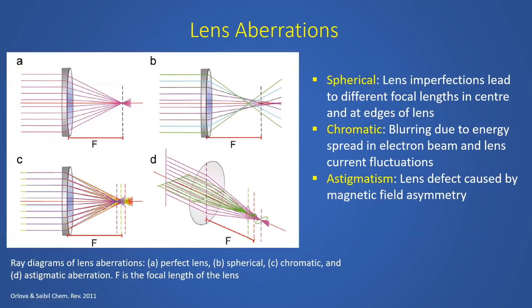These are the lens aberrations that you have typically with any microscope: spherical aberration, chromatic aberration, and astigmatism. Spherical aberration basically results from lens imperfections, so you have different focal lengths in the center and the edges of the lens typically. This is where the apertures come into place. You can cut off the peripheral electrons by using proper apertures. Chromatic aberration is basically due to blurring from different energy spreads in the electron beam and current fluctuations. And astigmatism is a lens defect caused by magnetic lens asymmetry. This is corrected by stigmators.